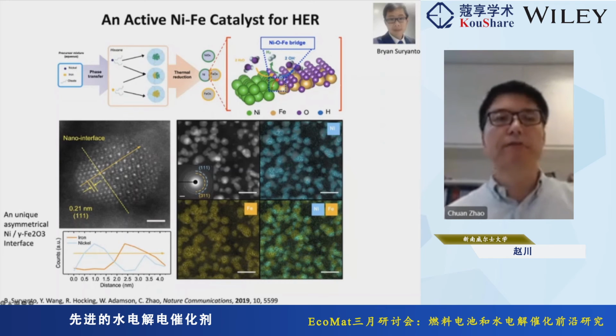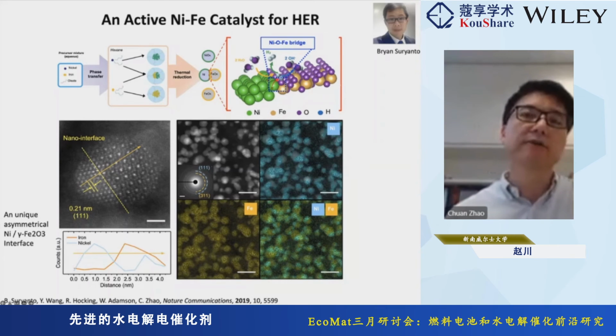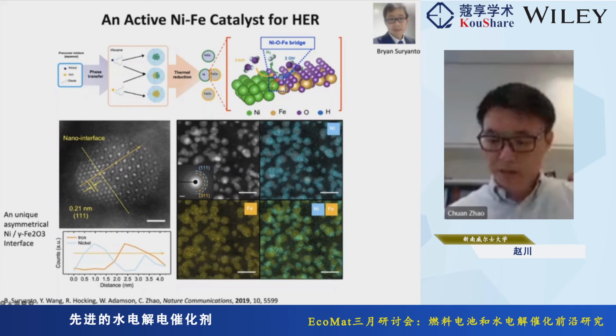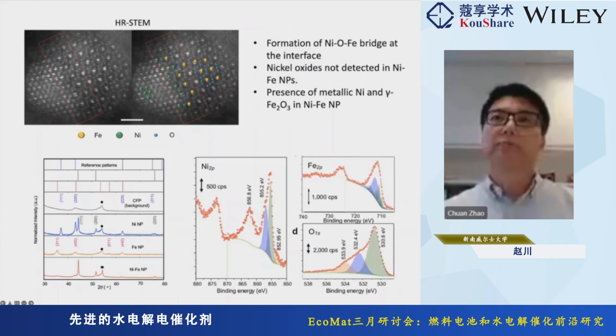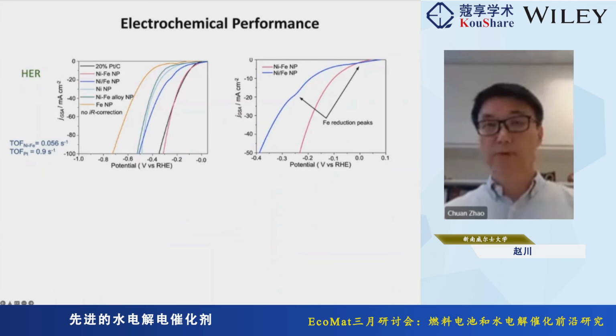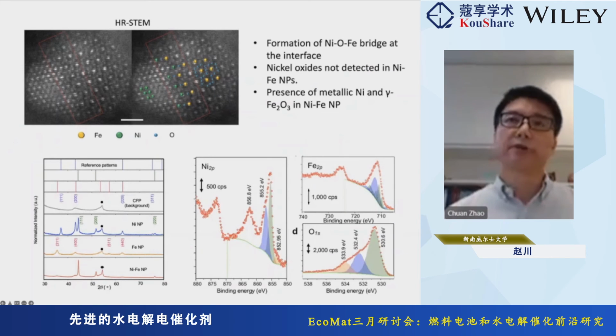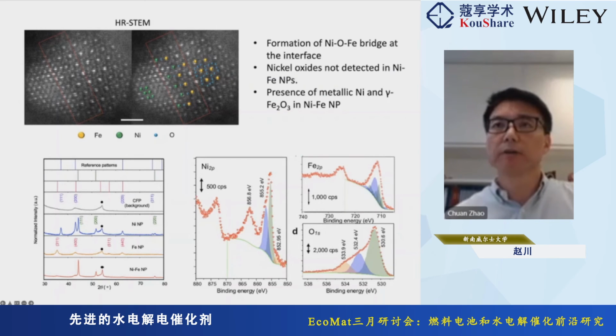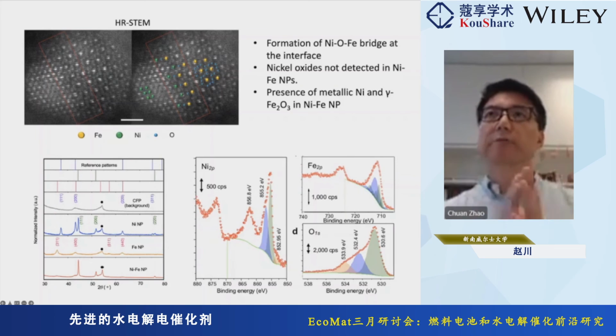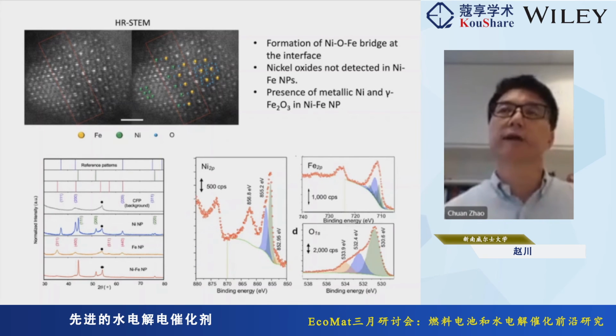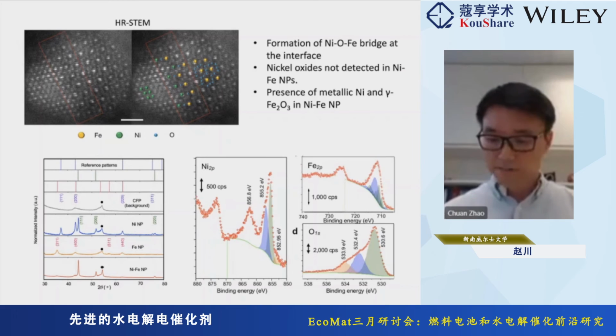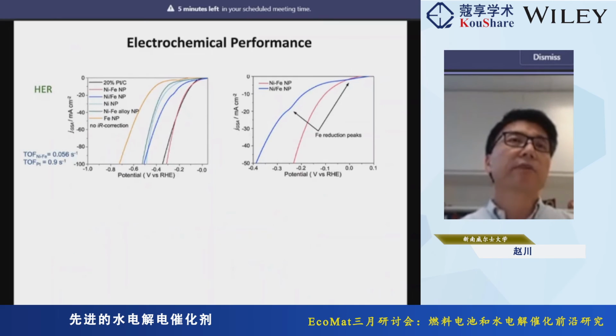Particularly from this EDAX line scan, we can see the distribution of the nickel and iron. We did a range of calculations to confirm there's no nickel oxide in the system. So we have metallic nickel and also the nickel iron phase in the nickel iron catalyst. And then the catalyst exhibits very good HER activity.